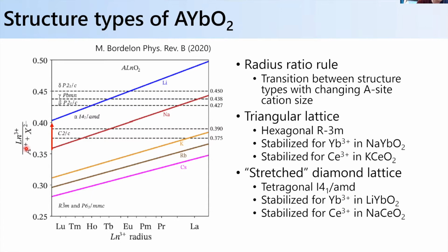And if you look at the ratio of the radius of the rare earth ion over the sum of the alkali and chalcogen ion radii as a function of the lanthanide ion radius, then you can find these crossover points where this ratio changes across a critical value, and then the structure type that's stabilized switches. So here's an example showing going from the R3 bar M structure, which is the triangular lattice, to the I4 1 over AMD, which is the stretched diamond-like lattice.